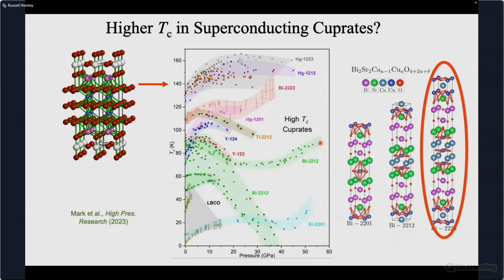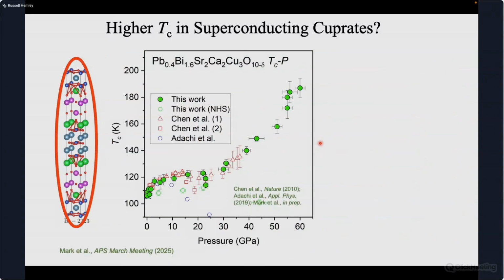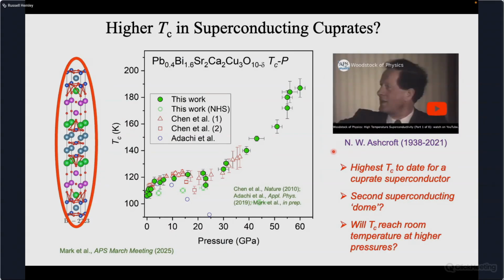He's been doing experiments extending this into the megabar range, and work he will present at the March meeting in a month or two. These are results now for TC for this particular cuprate, this BSCCO with some lead doping, and you see that there's a continued increase in TC with pressure. And the question is, is there a second superconducting dome, which is how we typically think about the superconductivity in these systems, and will it perhaps reach room temperature at the kinds of pressures we are able to reach with the hydrides?